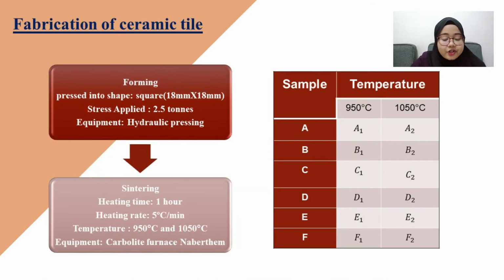Then the experiment continues with the fabrication, which is forming and sintering. In the forming process, the mixed materials were pressed into square shapes of size 18 mm times 18 mm by using hydraulic pressing. The stress applied is 2.5 tons. For the sintering process, the samples were heated at 950 and 1050 degrees Celsius by using a carbolite furnace. The heating time is 1 hour and the heating rate is 5 degrees Celsius per minute.